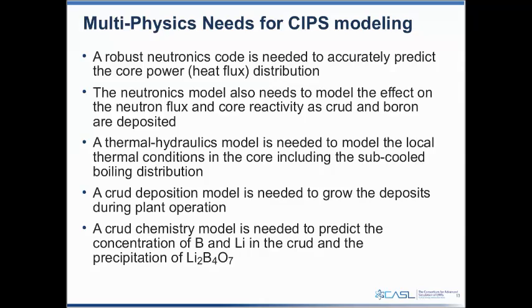We need the thermal hydraulics model to model local thermal conditions in the core, including the subcooled boiling rates and distribution, since that governs crud deposition. Then we need a model to actually model crud deposition and how those deposits grow with time during plant operation. In addition, we also need a chemistry model within the crud to predict how boron and lithium get concentrated, and when and how much lithium tetraborate forms.